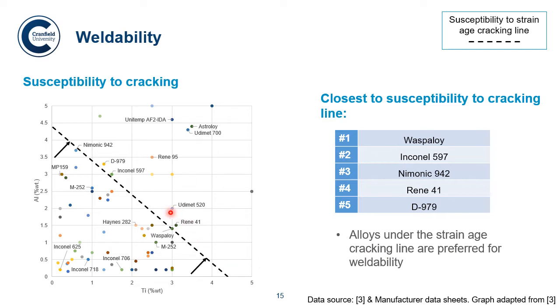And so the top alloy we got was Waspaloy, which is pretty much on the line, followed by Inconel 597, which is this alloy, which is just over the line a teeny bit. And then we have Nimonic 942, which is just under the line up here. Rene 41, which is slightly over the line. And D979, which is this one here, slightly over the line.